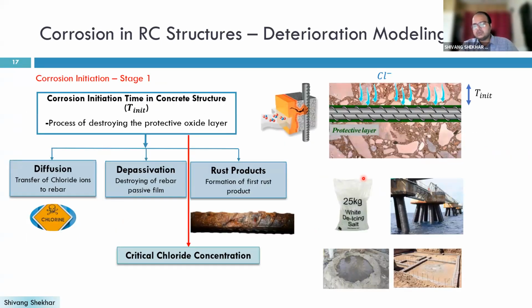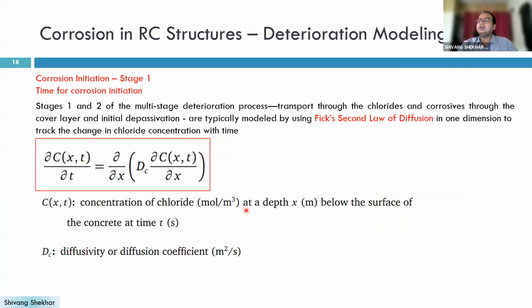When the chloride ions diffuse, and the surface chloride concentration reaches the critical chloride concentration, only then does the corrosion initiate. That leads to the formation of the rust product. Remember, this reinforced concrete member has some kind of protective film. This protective layer depends on the cover depth and the water cement ratio. There are several chemical characteristics that delay the corrosion initiation. If you see just the concrete cover depth, the larger the concrete cover depth, the more the corrosion will be delayed. Now there are some researchers, and we should be thankful for these researchers.